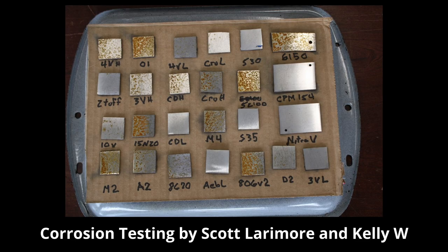In terms of corrosion resistance, I've never tested this steel. I haven't tested non-stainless steels that much. It hasn't been a priority for me, not something I've really looked at in the past. But I did find a set of tests done by knife maker Scott Larimore along with Kelly W. And they reported their results on the Bushcraft USA forums. So Scott, he treated a bunch of coupons from various steels. Then he ground them and he sent them to Kelly, who lives in a humid place. And so he just left them out in the elements. And then they looked at them to see which ones rusted. Now, there's a bunch of steels here. And also, some of them were given a low temperature temper of around 400 degrees and a high temperature temper of around 1000 degrees.